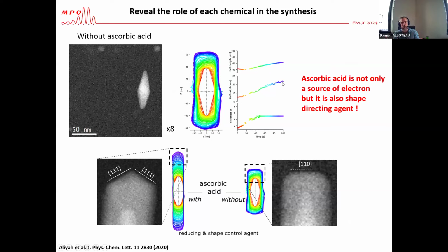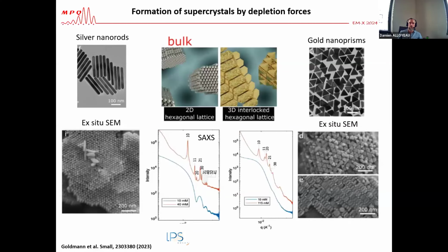So it gives also the possibility to reveal the role of each chemical agent during the synthesis. And here the role of ascorbic acid is a source of electrons to reduce your metal precursor, but it's also a shape directing agent that drives the anisotropic growth of silver nanorods. So for this experiment, we were very happy. The process observed in the liquid cell and at the bulk scale by SAXS and absorption spectroscopy worked well. Now I'm going to show you another experiment with the same type of object, where we